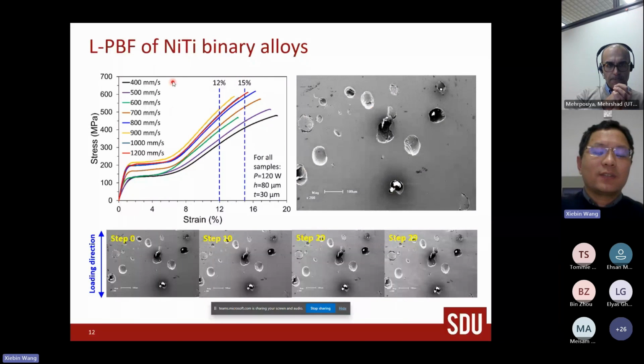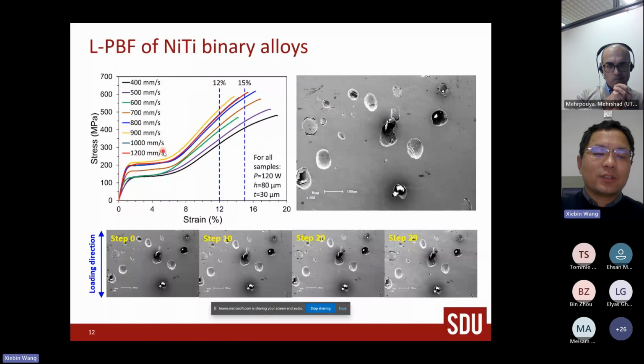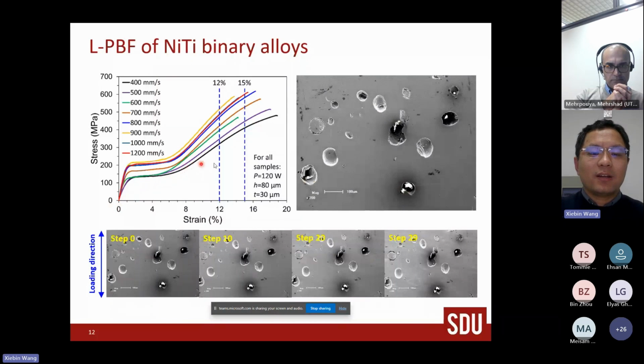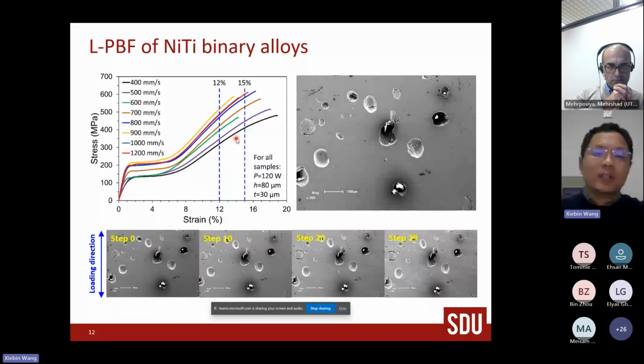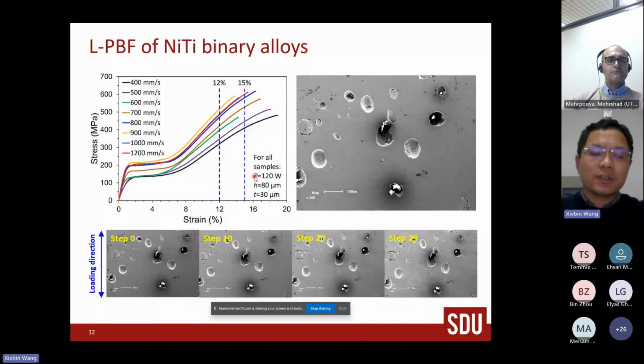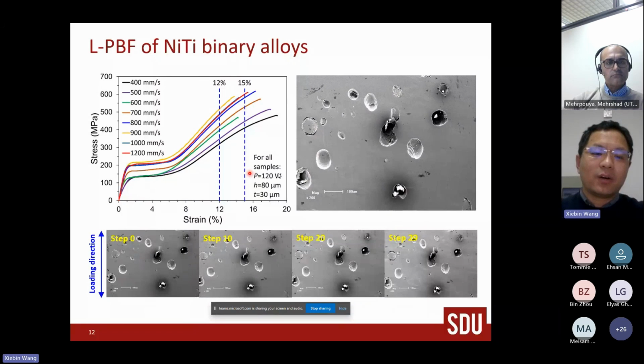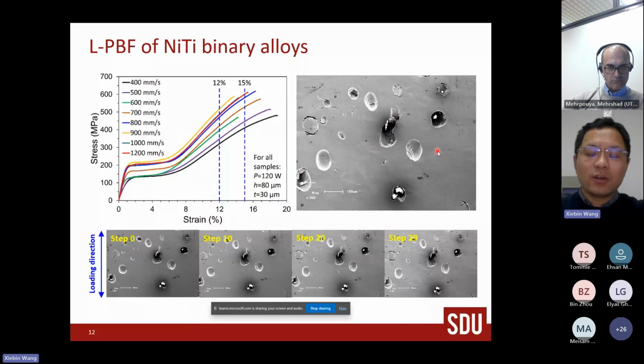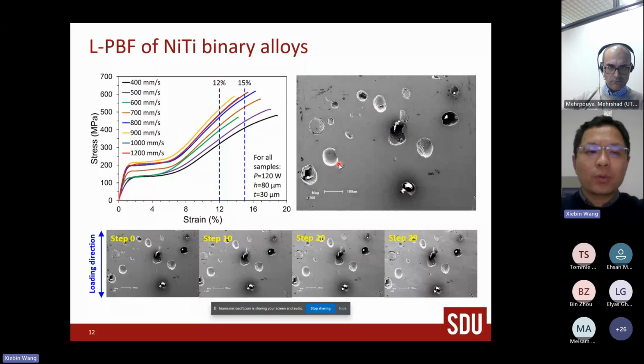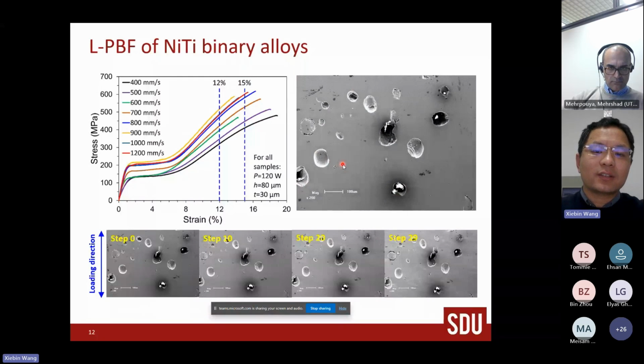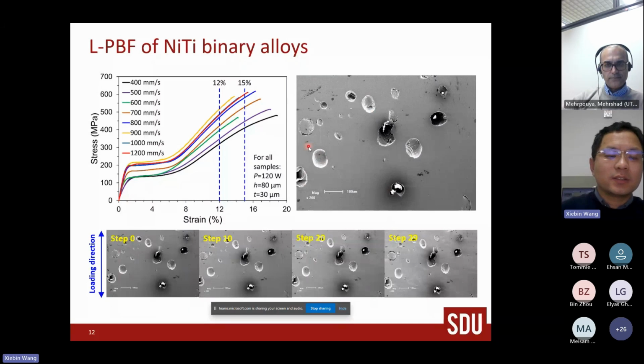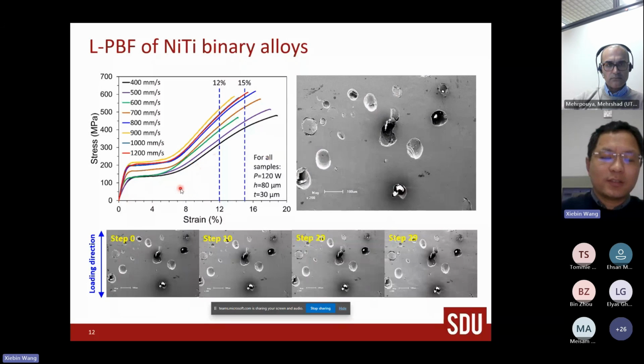But interestingly, if we change this scanning speed from 400 to 1,200 millimeter per second, the ductility or the total elongation of these samples is almost the same, all higher than 12%. It means that even if we have such a lot of large keyhole pores, it doesn't undermine the ductility of this material. So it's quite different from other alloys like aluminum and titanium alloys.